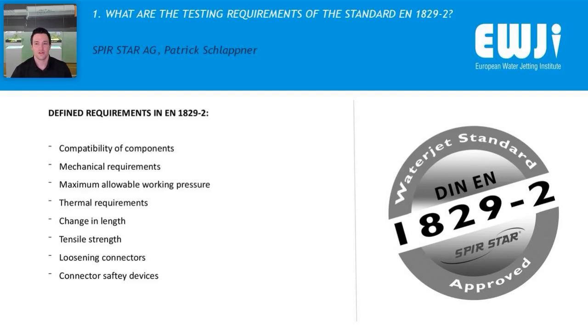All in all, the following requirements are defined in EN 1829-2. Compatibility of components. That means that hoses and fittings have to match each other. Mechanical requirements. Here, all components, hoses and fittings, shall not fail under the maximum working pressure. For hose lines with maximum allowable working pressures up to or equal 3000 bar, the safety factor has to be 2.5 to 1. Hose assemblies with a maximum working pressure over 3000 bar have a safety factor 2 to 1.